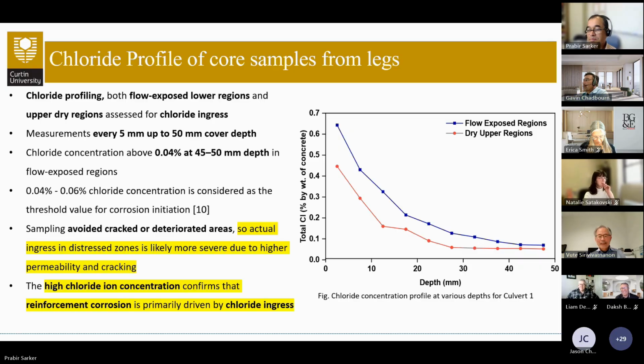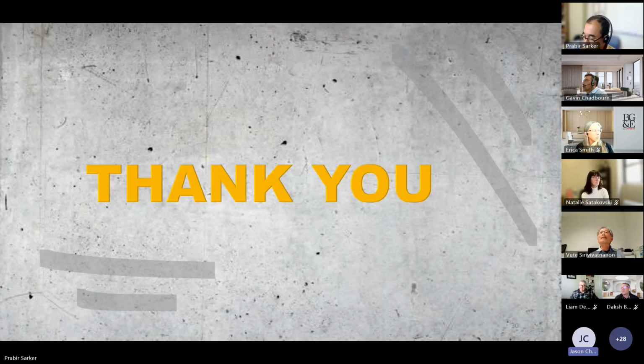Hello, go ahead Jason. Yeah, I put a little note in the commentary. Up to certainly 50% slag is able to be done, and is done, in culverts, I've seen it done in culverts. We've certainly done it on tunnel lining segments and the like for infrastructure work. So that was my suggestion in the comments, that taking the slag up to 50% or higher is quite reasonable because it doesn't seem to impact the early strength very much.